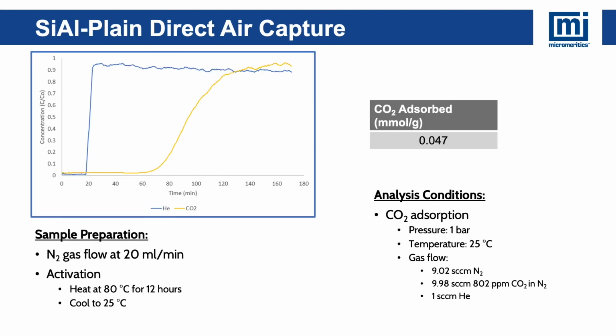So shown here, we have a breakthrough curve for our plain silica alumina, and we can see that our CO2 adsorbed is very small, only about 0.047 millimoles per gram. However, once we loaded it with PEI, we see roughly a 4-fold increase in our CO2 capacity, reaching a capacity of about 0.166 millimoles per gram.